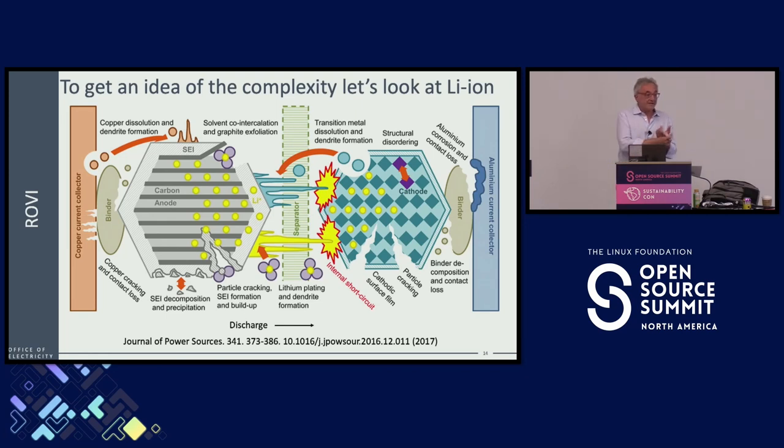Because maybe the mixing wasn't right, or the coating wasn't right, or the rolling wasn't right, or, people say, it was 72 degrees outside with 72% humidity. Or like the funny story: a friend of mine, whose family is originally from Sicily, tells this story that at A123, a battery company that came and went out of MIT, they were having failures because there was a higher content of salt in their electrode. They asked, why is there salt in the electrode? This is crazy. Until they figured out that the workers would buy burgers with fries and eat the fries in the clean room. What?